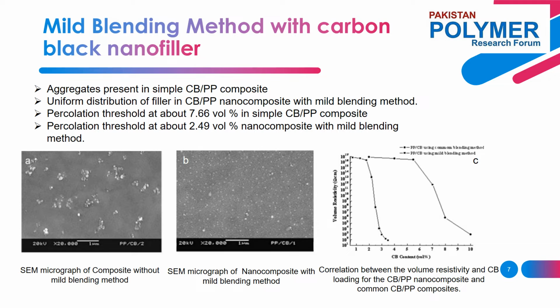In order to observe the impact of the mild blending method on dispersion of filler, the carbon black and polypropylene nanocomposite and the simple composite of carbon black and polypropylene were analyzed using SEM. The SEM micrograph of the common carbon black and polypropylene composite, as shown in figure A, showed that most particles were aggregated together, and the aggregates were detached from each other. At higher carbon black content, the scale of aggregation increased, which was caused by the connection of carbon black aggregates.